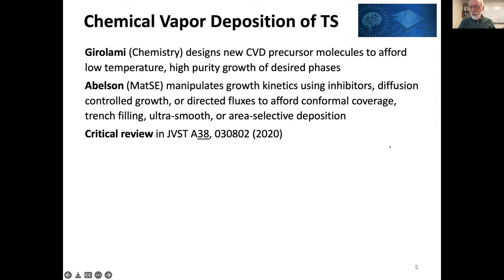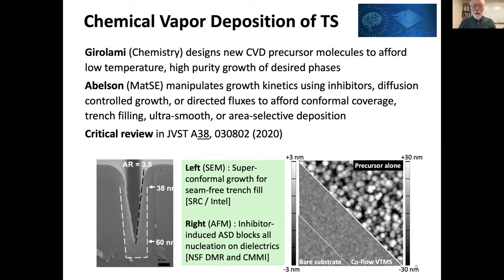This is a huge body of work. We published a critical review of almost 20 years worth of work in this citation. So let me here give two examples of some relevance. On the left, some work we did under SRC support with Intel. This is filling a trench structure with a dielectric. You can see here on the lower left that in fact, the growth is doing something impossible. It is super conformal. It's growing faster in the bottom than higher up. It forms a V shape, and then this V grows up and out of the material. So you can get seam-free growth. I will just allude to the fact that we're currently trying to do this with silicon nitride, and that involves some precursor magic that Greg and his group are doing.